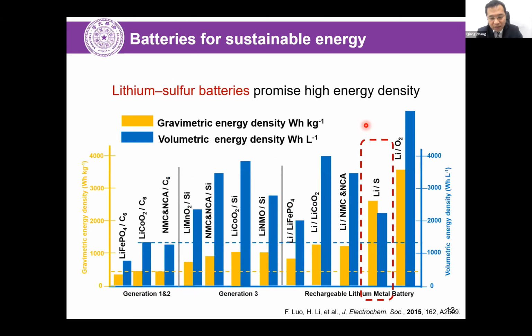So with this consideration, we try to plot the cathode versus anode for different systems. And it is found that when carbon is replaced by silicon, the energy density, whether gravimetric or volumetric, will be increased gradually. If the anode is fully replaced by a lithium metal anode, a high energy density is always achieved. However, there are several challenges.